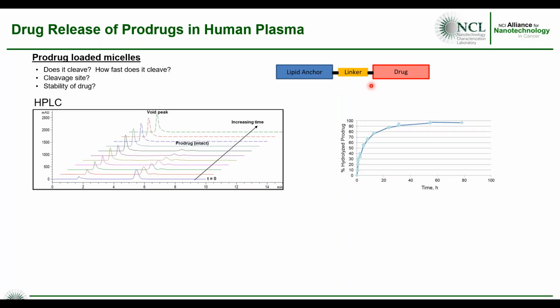So we came up with an HPLC method here, where instead of looking at the cleaved drug, we actually looked at the intactness of the prodrug itself as a function of time. So at time naught, we have a peak here that corresponds to the prodrug intact. As you incubate this with plasma, with time, this drug will be cleaved, and this prodrug peak will decrease with time. You can then convert this to your hydrolysis rate of your prodrug.